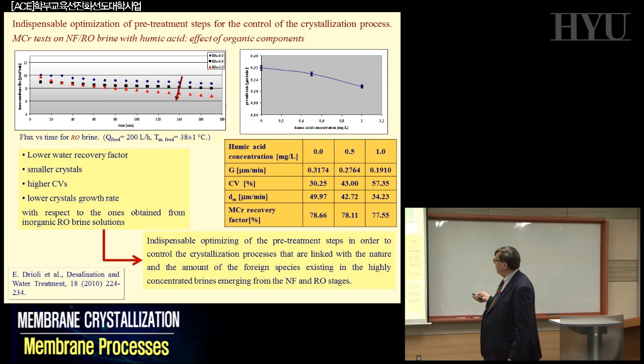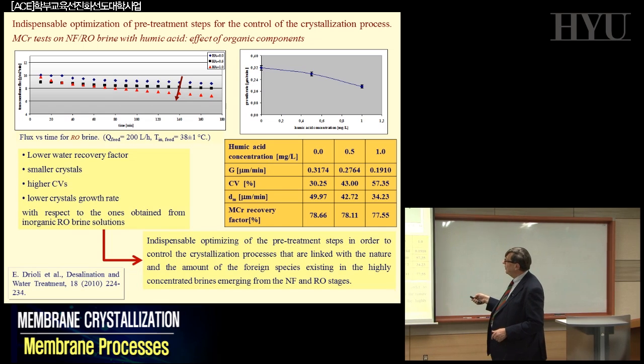You can have, for example, the relationship between the different geometry of the system going down significantly. That is, increasing the humic acid concentration, you deviate from the initial performance. The transmembrane flux, if I am right here, that was transmembrane flux as a function of time, is going down, increasing the amount of humic acid. So this is one of the effects.